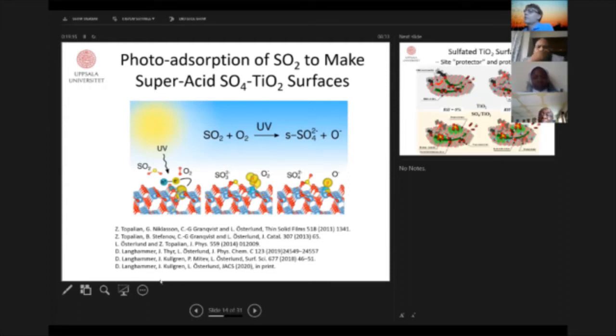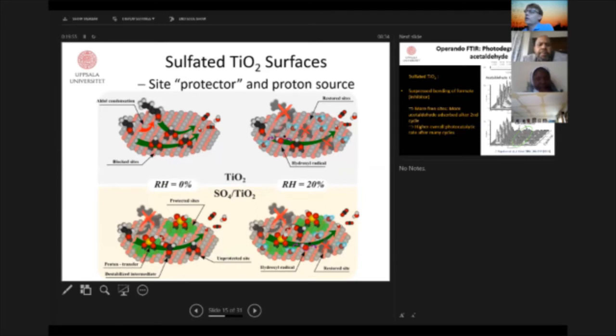And we have explored this method of how to make these surfaces super acidic. It should be known that sulfated titanium is a known catalyst. It's prepared by quite harsh methods in powder form, and we have now come up with a scheme to make it synthetically on films under very mild conditions. And these are the publications here, also in my slides, which I will distribute to the conference, on how to make sulfated titanium with these attractive properties. But given that you have these sulfated titanium surfaces, what you do is bind them on the sites which are prone to deactivation, and then you mediate this proton transfer reaction to facilitate reaction. You lose some sites, but you gain the long-term activity. So this is quite nice, and it works in water as well.